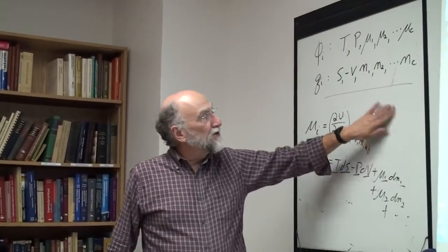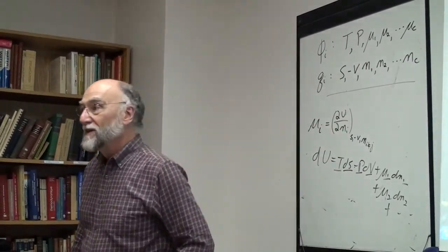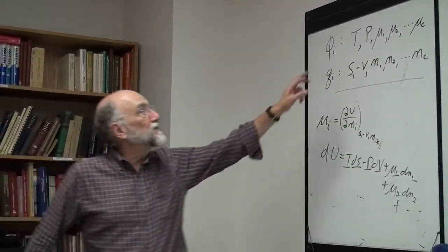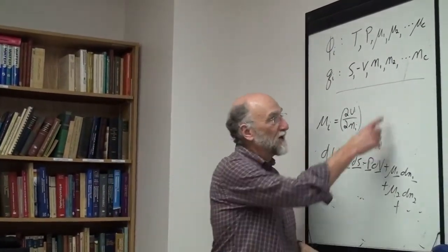First of all, in some phase diagrams you can draw tie lines, and in other phase diagrams you can't draw tie lines. Like I said, if you have an isopleth, you can't draw a tie line because the phases don't have a composition in the plane. If you're plotting one variable versus another, and you're keeping only potential variables constant, then since all phases have the same T, the only variables... a phase diagram has a y-axis, an x-axis, and a whole bunch of variables that are kept constant. If the only variables kept constant are potential variables, they are the same in every phase. Therefore, all the tie lines are going to lie in the diagram.